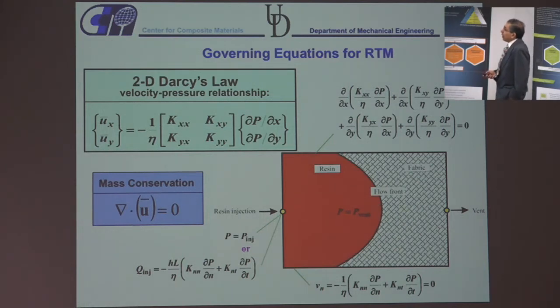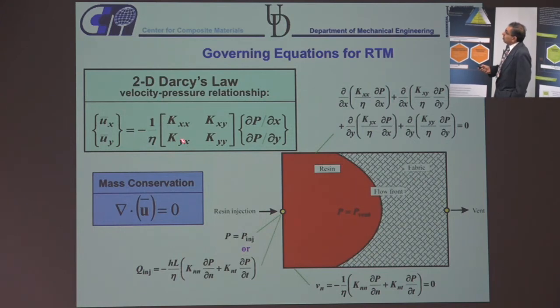So first, the macro scale: the governing equation was Darcy's law. In 2D, you would write down that average velocity is proportional to the pressure gradient, and the proportionality is basically the permeability of your material, which you have to characterize because that comes in as an input. The difference from normal Darcy's law is that it's anisotropic, so I could have different resistances in different directions, which I can express with this permeability tensor.